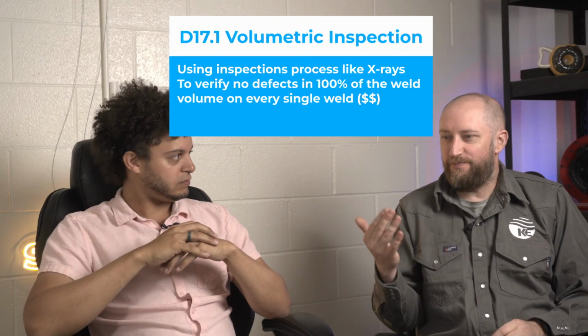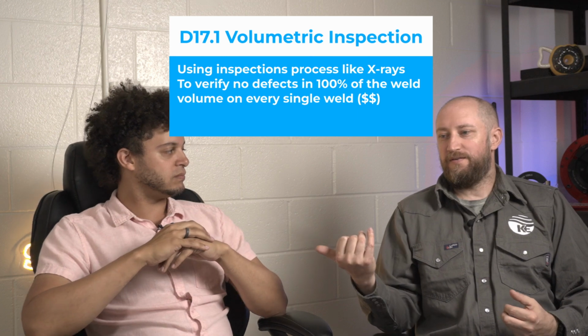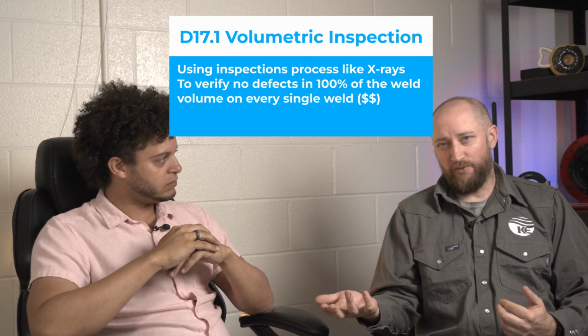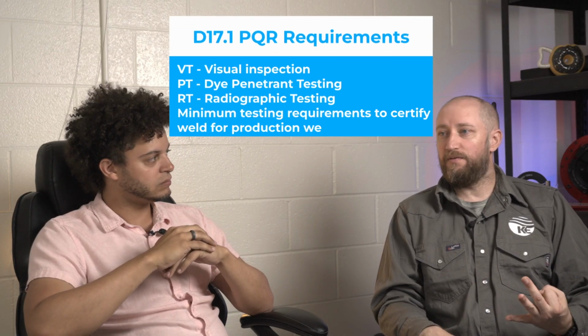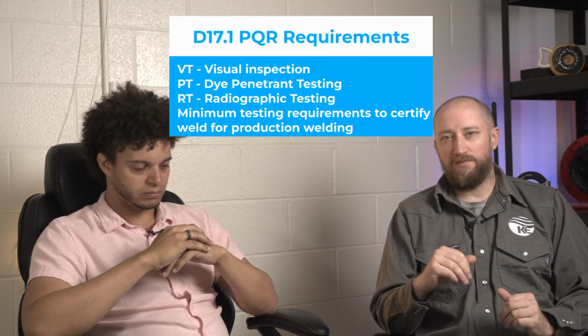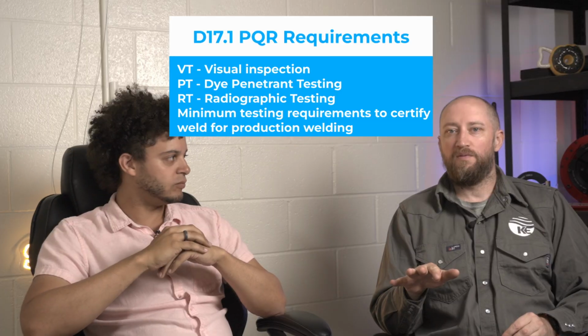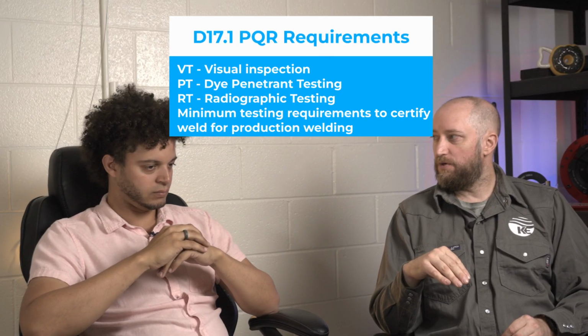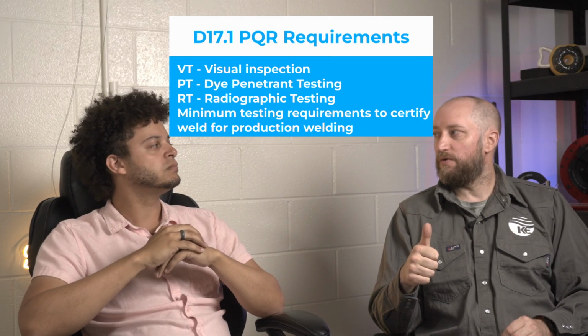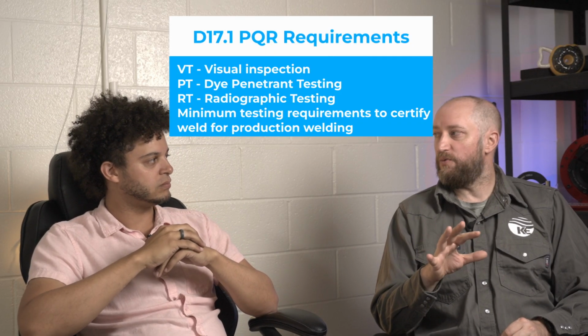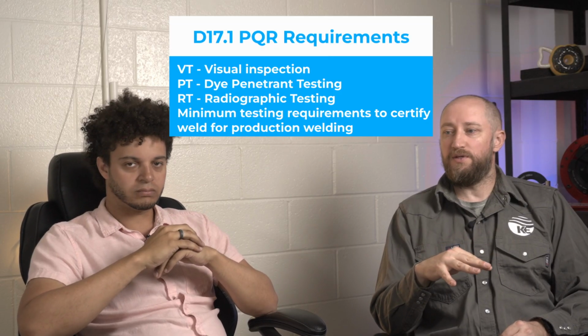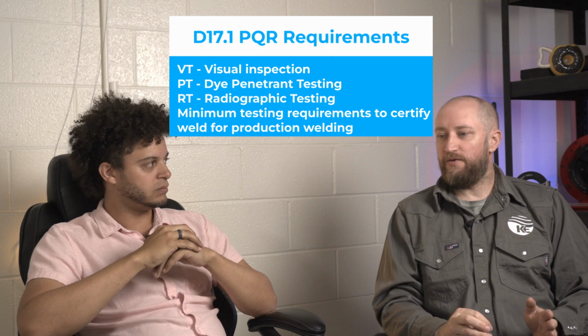Yeah, and that's the peculiarity we talked about earlier: in the newest edition, the 2024 edition of 17.1, to run a PQR, you do VT, PT, and RT. No tensiles, no bends, no hardness, no CVNs, no corrosion, no anything. But if you're running Class A in production, you're getting 100% RT. Okay, so that's not very frequent in the ASME world where we're doing 100% RT. And so on the front end, qualifying procedures in 17.1 is really cake. It's really easy. But your welders have got to be really good.